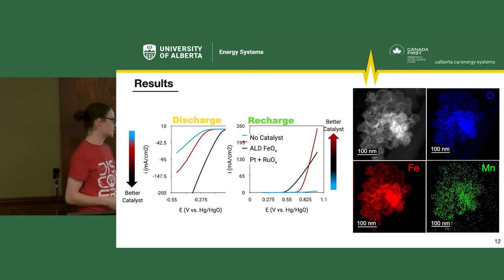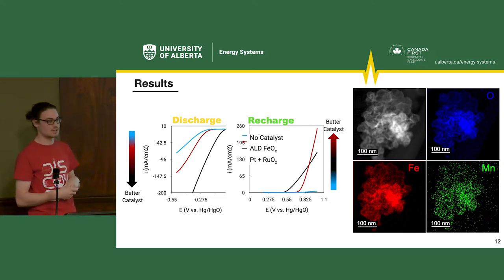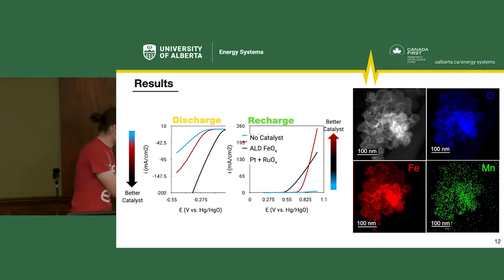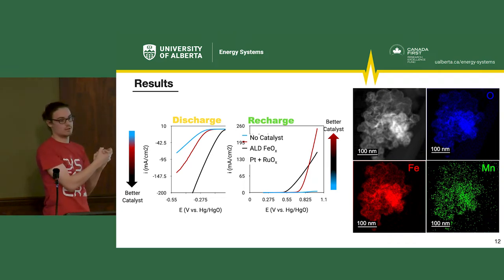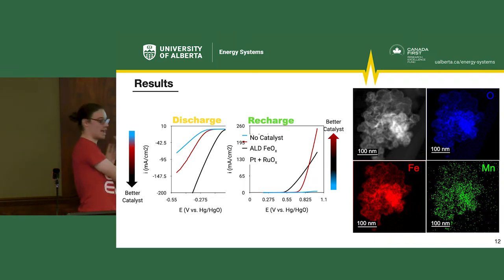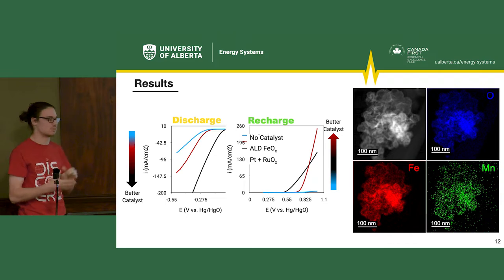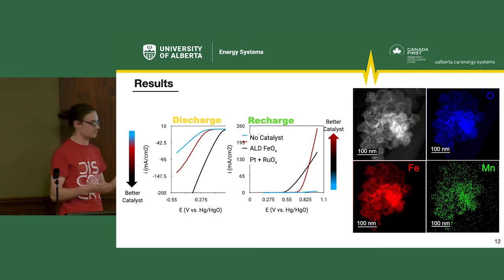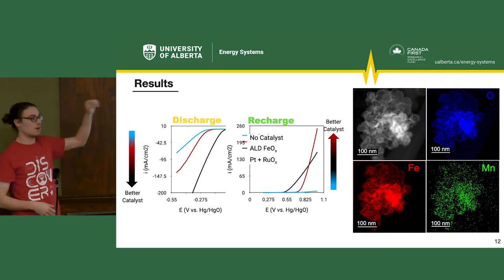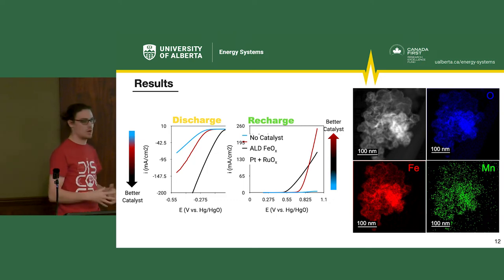And in that case, looking at platinum versus my iron oxide, after a certain potential, I can get more current with my iron oxide. So my iron oxide is actually more active towards that recharging reaction than, say, the platinum or ruthenium oxide, those precious metals. So that's very promising. On the right there are X-ray maps of my material.